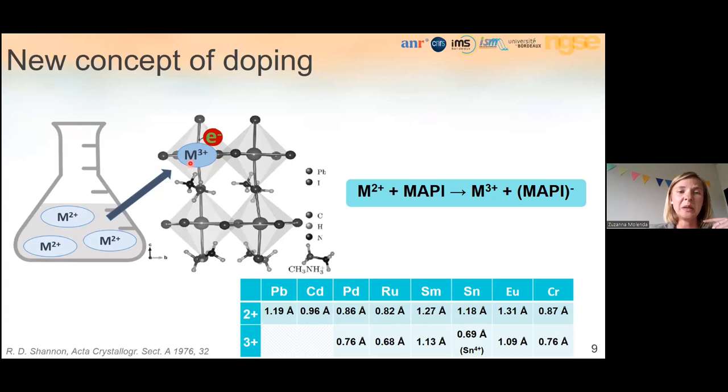As a control experiment, I also prepared samarium triiodide and doped the perovskite layer using the same technique. I observed none to insignificant increase of conductivity, showing again that it must be samarium 2+ and not 3+ that is responsible for the doping effect.